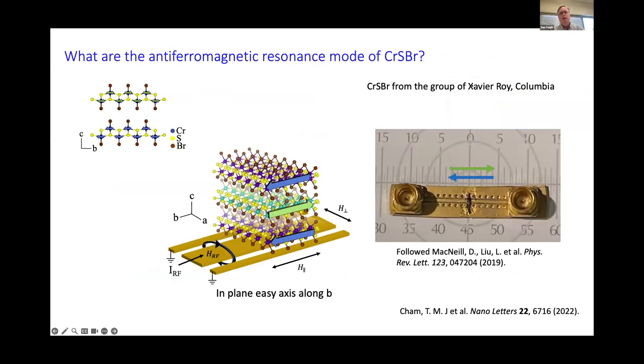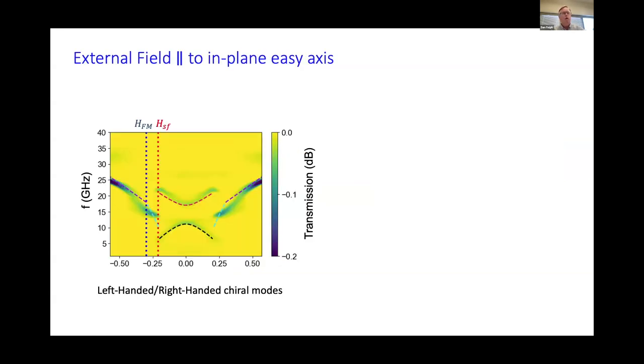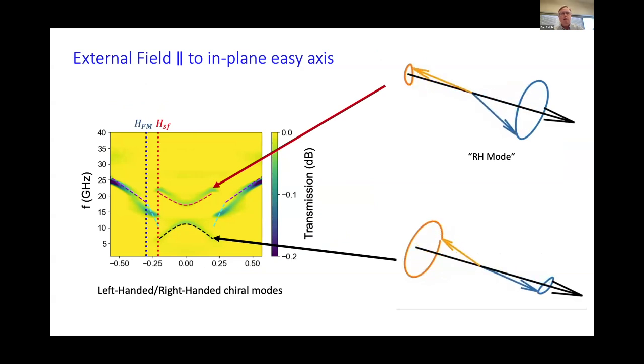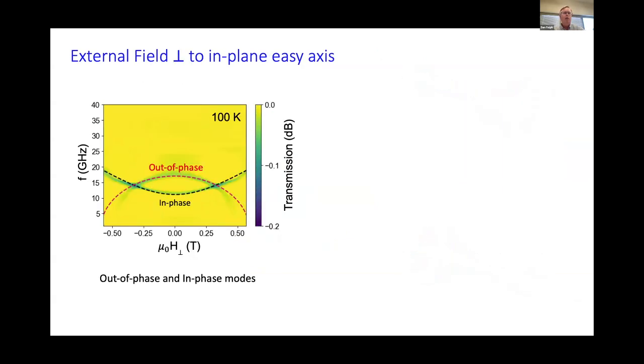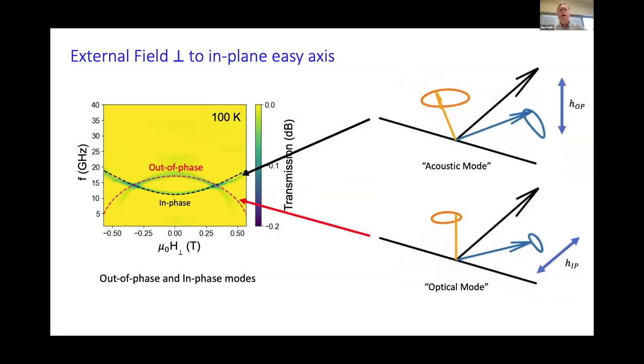To begin our work, we wanted to know where the modes were, and so we did some of these macroscopic experiments, just resonant absorption using coplanar waveguides, trying to understand what the different modes are. We were able to characterize what the antiferromagnetic modes are and understand all the magnetic parameters, the anisotropies and exchange fields that govern these modes. If you apply an external field parallel to the in-plane easy axis, you can see right-handed and left-handed modes. If you apply a magnetic field instead perpendicular to the easy axis, you see acoustic and optical modes. But all these can be understood in a Landau-Lifshitz-Gilbert kind of way.